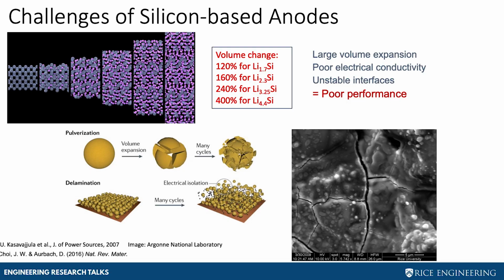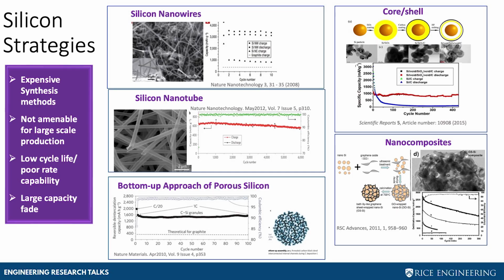Really, there's a big challenge when you think about silicon. As it alloys with lithium, it goes through a large volume expansion. It's like a sponge, so it's going to swell. And as it swells, silicon is inherently a crystalline material. It's going to fracture, it's going to crack. There's a lot of stresses in the material on here. So that large volume expansion leads to poor electrical conductivity and that really then leads to poor performance on here. So the past 2 decades, there's been a number of research groups working on different strategies to think about for silicon. Most of them involve nanostructuring silicon, looking at silicon nanowires, silicon nanotubes, being able to create some type of porous structure, core shell structures, nanocomposites, so the works on here.